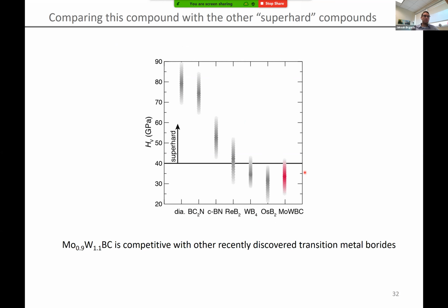Well, molybdenum tungsten borocarbide is better than osmium diboride. We're competitive with tungsten tetraboride, which, as I mentioned, is being commercialized. We still fall below these types of compounds, but it's worth highlighting that this is a compound that had not been studied before, and we picked it out of our sorting diagram. More importantly, it contains molybdenum, which is definitely not as expensive as rhenium or osmium.